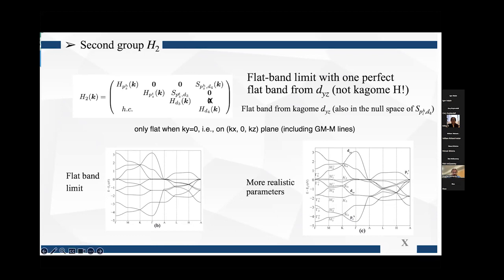But the point is that these unperturbed Hamiltonians, which are kagome, which, for example, HD4 would be an unperturbed kagome Hamiltonian, have a single flat band. HD3, D4 and D3 are XZ and YZ. HD3 would have a flat band. They do couple to other terms, and these coupling terms, which are called S, they actually don't have small values. I mean, they have as large values as the in-plane hopping of the D4, effectively. And then what you find at the end of the story is that you're going to have flat bands, or real flat bands, only on some lines.